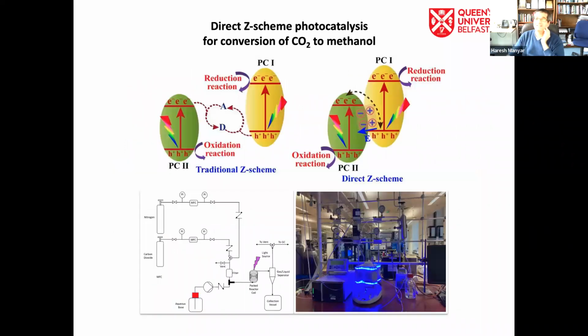This is called direct Z-scheme photocatalysis. Again, this is based on metal oxides. In this case, we have a traditional Z-scheme in which you combine two metal oxides. When you shine light on one metal oxide, it generates electron-hole pairs. As you can see on my screen here, the hole is in the valence band and the electrons jump up to the conduction band. Then, with the presence of the other metal oxide and charge transfer agents, these electrons from the conduction band of one metal oxide can be transported to the other metal oxide. If you transport them to the hole of the other metal oxide, they combine with the hole of this second metal oxide.